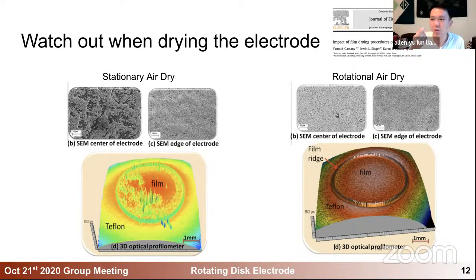If you just let the RDE electrode sit in the air, stationary, and air dry, sometimes you can end up with really unevenly distributed particles or materials across your electrodes. And this group, interestingly, flipped the RDE setup upside down, and while their electrode is drying, they apply a really slow rotating motion, and the active particle material can spread out evenly across the electrode surface.